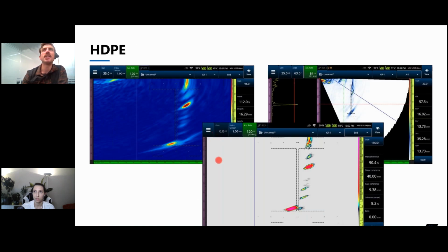But another use case that's not in metals is with HDPE. This is something that we've just recently looked into a bit more, but we're having promising results in these kinds of materials, with a better signal-to-noise ratio and seeing defects much more efficiently using PCI versus, say, TFM or phased array. The big defects in TFM are still visible. We can see a lot more detail in the deeper section of the part using PCI, and same thing with phased array, where we can still see the deeper portions of our part, but we're not getting nearly as much detail in the middle as we are with PCI.